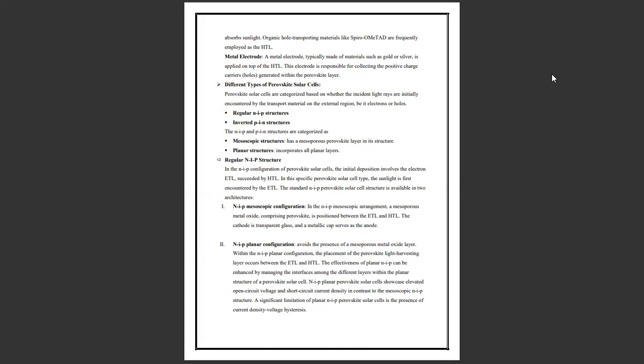Within the NIP planar configuration, the perovskite light harvesting layer is placed between the ETL and HTL. The effectiveness of planar NIP can also be enhanced by managing the interfaces among the different layers within the planar structure of a perovskite solar cell. NIP planar perovskite solar cells showcase elevated open circuit voltage and short circuit current density in contrast to the mesoscopic NIP structure. A significant limitation of planar NIP perovskite solar cells is the presence of current density voltage hysteresis.